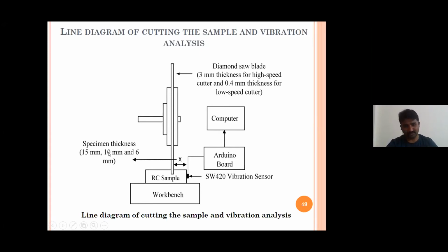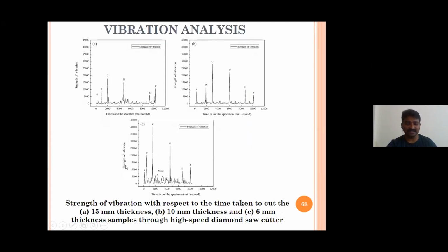So to check what happens if I take 10 mm and 6 mm, we have tried with 3 different thicknesses, showing the effect of vibration on those 3 thicknesses. As you can see, this is A, this is 15 mm thick, this is 10 mm thick, and this is 6 mm thick. Do you observe? We have kept the scale same, 0 to 45, 0 to 45, and 0 to 45. The x-axis is slightly changing depending upon the time it took for cutting that sample.